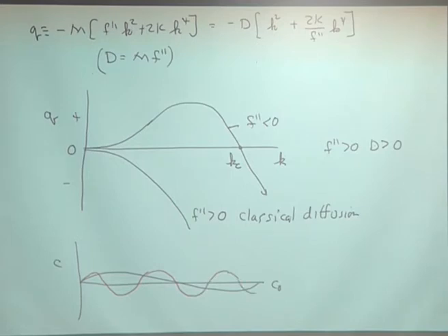So you can see it has the same amplitude, but now look at what's happening here. The gradient is higher than it is here. And so what happens when the gradient goes higher? Remember, we put in this gradient energy effect that said the higher the gradients, the more it increases the energy. The gradient energy coefficient is positive.